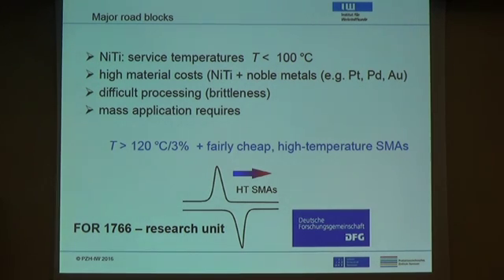So if you're really interested in, say, mass applications, what we need is a temperature beyond 120 degrees C, something like 3% strain, fairly cheap materials, and that's it. We try to address this within a so-called research unit sponsored by the German Research Foundation, where we try to push up the temperatures of the phase transformation. Today, I will only talk about one issue, the cyclic stability of these materials, because this is a key issue.